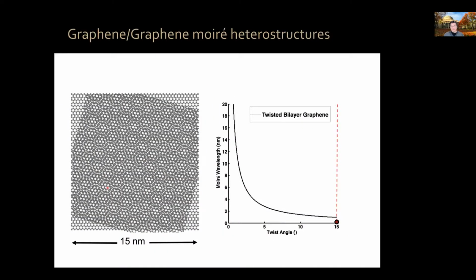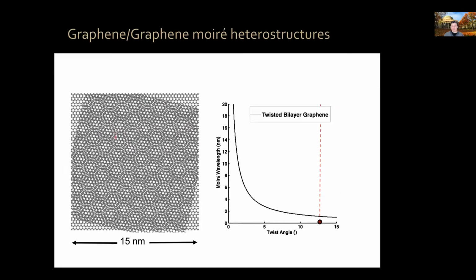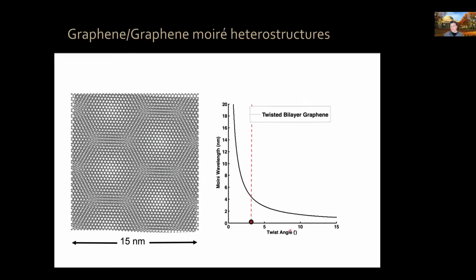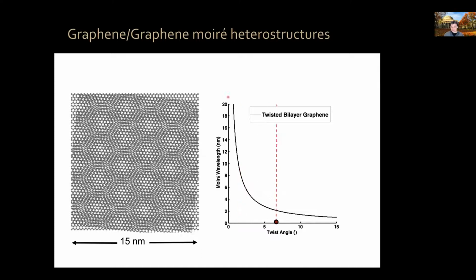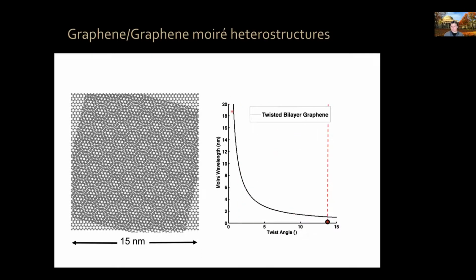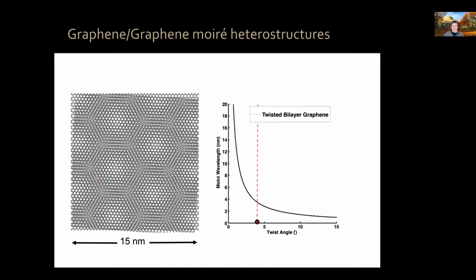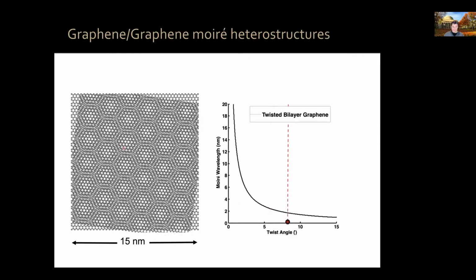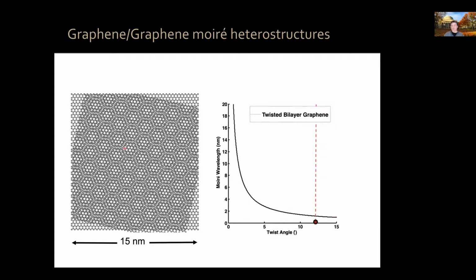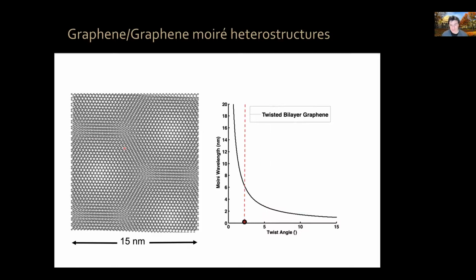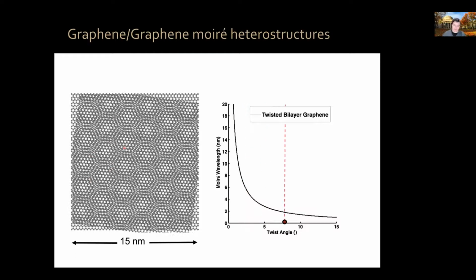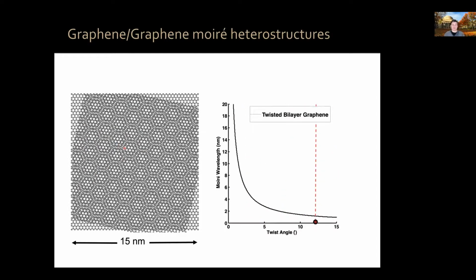Now, when we put graphene on top of graphene, we create a moiré heterostructure where the moiré wavelength, the distance between the soccer balls that you see here on the screen, depends on the twist angle. In particular, for low twist angles, it is inversely proportional to the twist angle. Now, this is what happens when you put graphene on graphene in real space. What happens when you look at the momentum space or reciprocal space, and therefore what happens to the electronic structure?